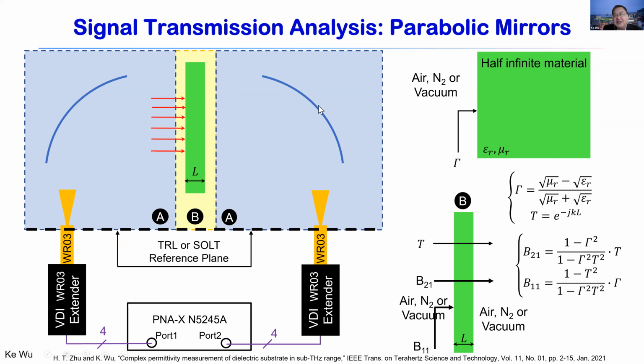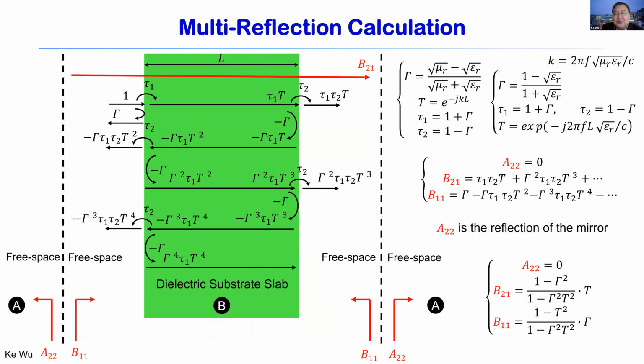And so for this kind of generalized material, for example, if you consider permeability and permittivity, for the planar wave transmission over this low loss material, you can have the reflection coefficients here or transmission through this L. L is the thickness of the material under test, and of course you can also develop transmission and reflection coefficients through the generalized formula. I will not go through this detail here, but one of the most important techniques which has been used in the community is called the multi-reflection calculation.